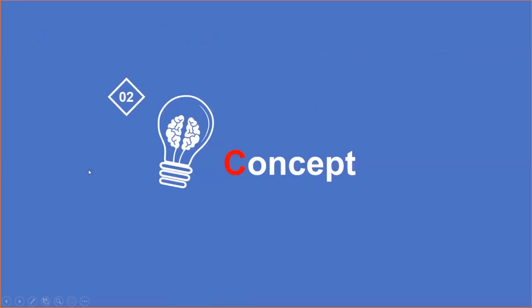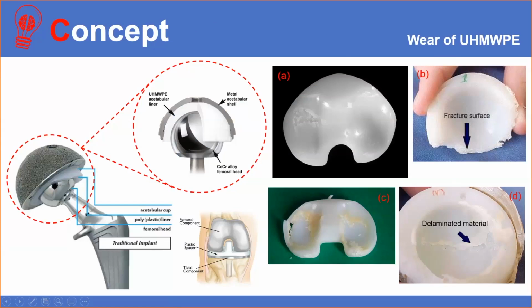Next is the research concept. Okay, the main principle for this research is the micro-bearing concept. Ultra-high molecular weight polyethylene has been used as a bearing material in total joint arthroplasty for more than 50 years now. The idea to replace the degraded cartilage with a polymer liner dates back to the late 1950s. At that time, Sir John Charnley chose polytetrafluoroethylene, PTFE, a low-friction polymer, as the bearing material to replace the natural acetabulum, articulating against a metallic femoral head for hip replacement. However, due to the overly low wear resistance of PTFE, it dramatically failed after a few years of implantation.